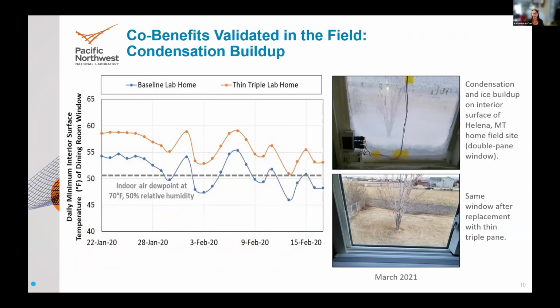Condensation is very important, and we see substantial benefits reducing the condensation potential on the interior surface of the glass. The photo that I'm showing to the right is a home in Helena, Montana. This is a double pane low-E window, so a cold window, up on the top that has actually ice buildup and condensation that's built up. It's a pretty high humidity home with young children in this bedroom, but we were able to clear up all the condensation issues with the higher performance triple in this field site.